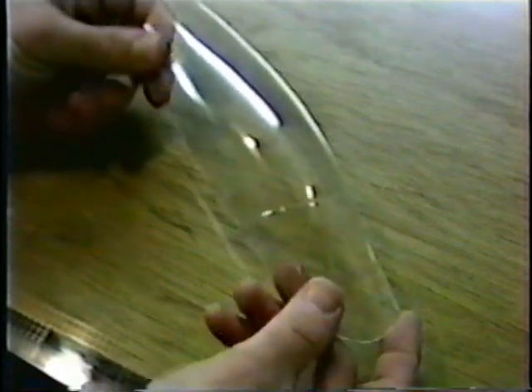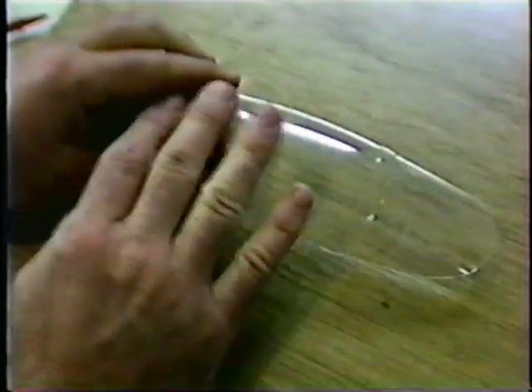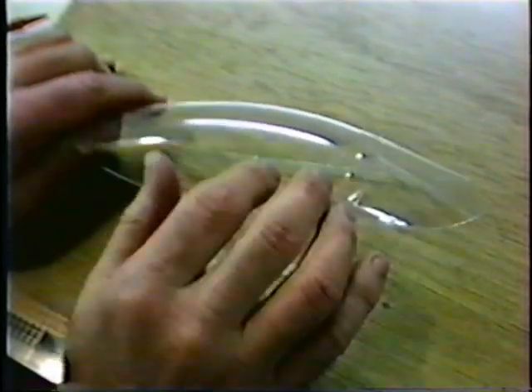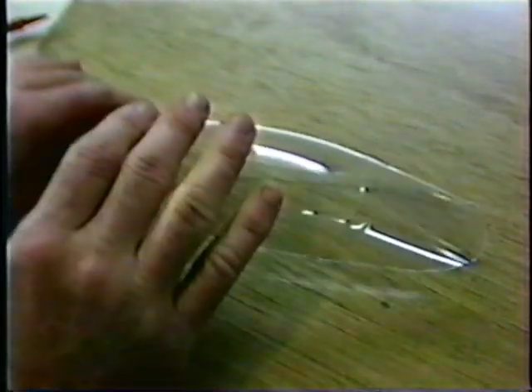So when you get to the point where you're going to paint the clear on the plane, what I do is I take all the tape off the canopy, get this edge nice and smooth, and spray a coat of clear right over the canopy. Now, if you spray over the canopy with clear, it's a good idea to scuff it up with 600 first, then spray it with one coat of clear. Not a lot of thinner. If you use penetrating thinner, high gloss thinner, retarder, you'll melt the canopy and it'll just go shh, which I've already done. One coat of clear at a time, let it dry overnight, maybe five coats altogether, and then buff